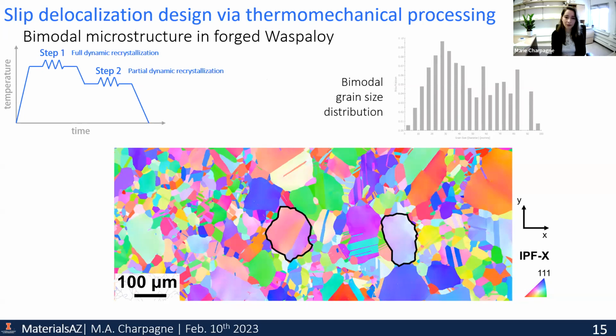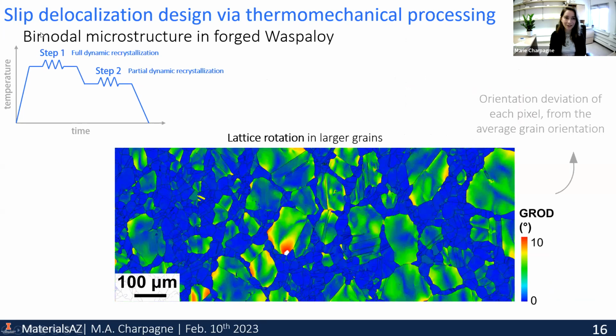Another characteristic of this microstructure is that in the grains that were formed in the first step, large dislocation densities remain and were added during step 2. And these high dislocation densities manifest themselves by large lattice rotations. Here I'm showing the same EBSD map, where you can see that those large grains have large rotations in their misorientation with respect to the average orientation of the grain. So this is a signature of the presence of geometrically necessary dislocations that are there to accommodate the humongous amount of strain that we put in during the second step.